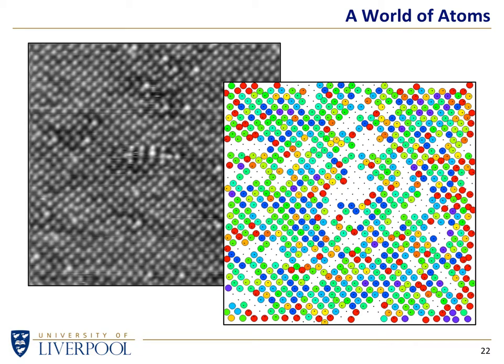And image processing allows us to find where the atoms are, and in this particular case, I colored each little blob with how far away from where you would expect it to be it is. In other words, the dark blue atoms are exactly where you would expect them to be if they were on this regular grid.